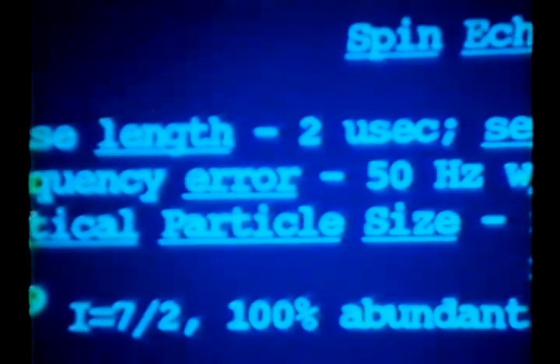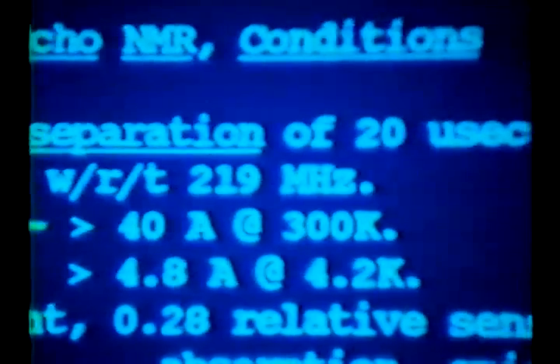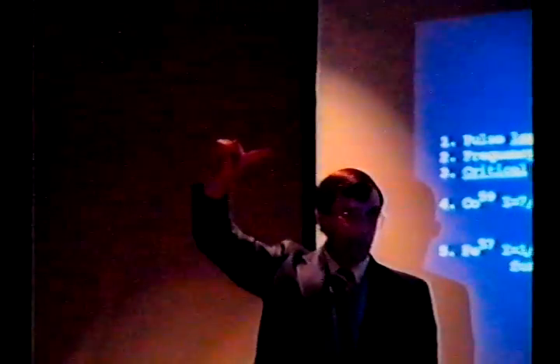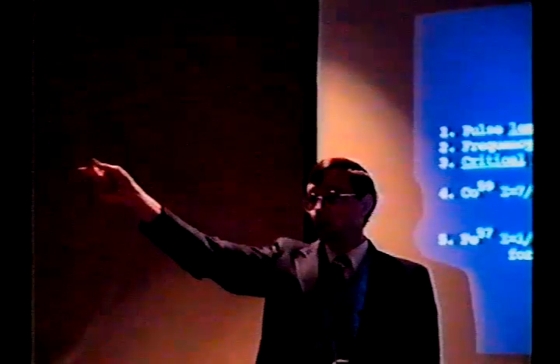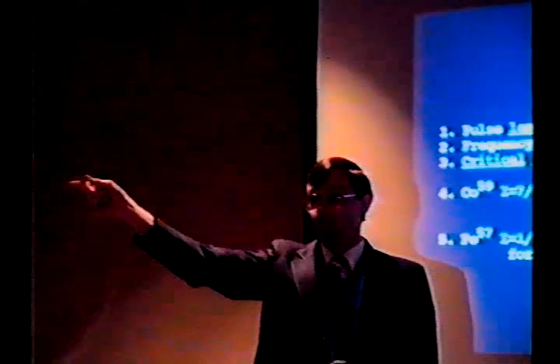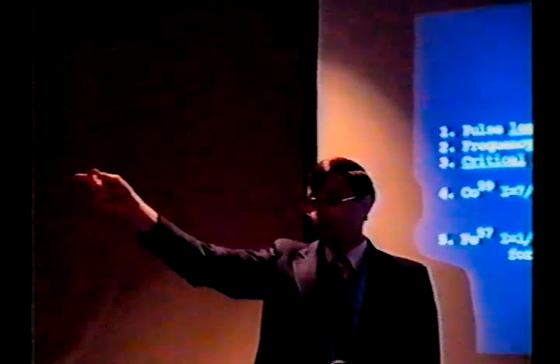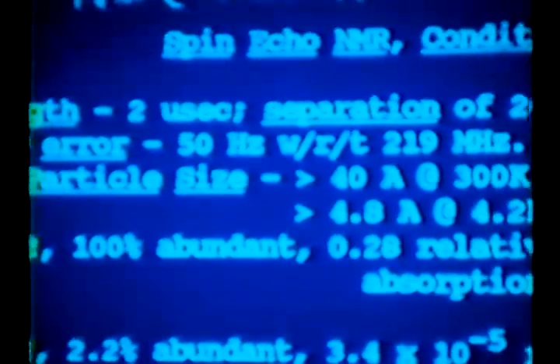What happens is the magnetization starts out, let's say, in the Z direction. You apply one pulse, and the magnetization goes down into the XY plane. You apply another pulse, and it goes back over in the same XY plane, 180 degrees out of phase, and that creates an echo. So you put in 2 RF pulses, and you have a separation between them. The frequency here is about 50 hertz with respect to a signal which is 219 megahertz.